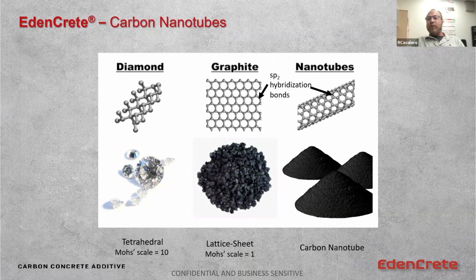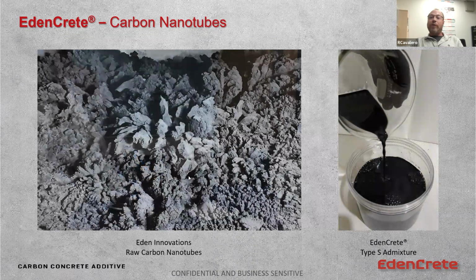And that's to say, if you envision several varying diameters of seamless pipe, all inside one another if you're looking from the end, okay? And so we grow those, and it's these sp2 hybridization bonds that occur at the apex of these hexagonal interfaces that give carbon nanotubes these really strong, really incredible properties that make them appealing for a lot of different applications. What you see down here on the bottom right is a picture of ground carbon nanotubes after we've processed them. When we first open our reactor, they look like this here on the left.